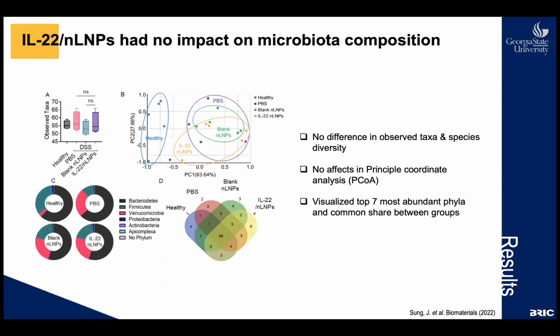As is well known, gut microbiota is responsible for 70% of our immune system. So we checked whether IL-22 lipid nanoparticle treatment affected microbiota composition or not. We collected the fecal samples throughout the study and analyzed the composition at the phylum level by whole genome sequencing. As we can see in the title of this page, there was no significant alteration of microbiota composition by the treatment. To tell you the result first.